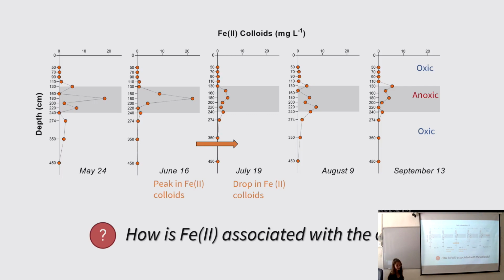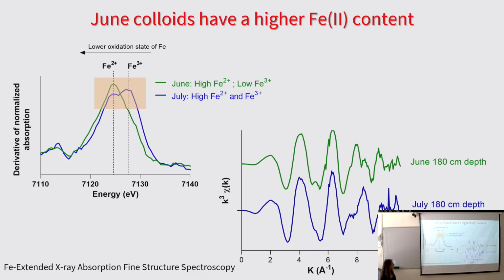with our colloidal assemblage. So we performed some more iron XAFS spectroscopy to learn about the oxidation state in various species of iron in our sample. Here I'm presenting the XAFS data for the June and July samples. This is at 180 centimeter depth. And on the left here is the derivative of the absorbance, which shows us the oxidation state of iron. So you see here in both June and July we have a combination of iron 2 and iron 3, but higher abundance of iron 2 in June and higher abundance of iron 3 in July.